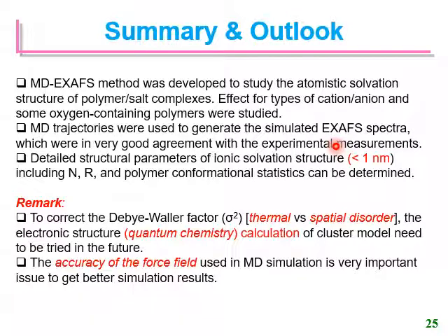So, summary and outlook. The MD-EXAFS method was developed to study the atomistic solvation structure of polymer salt complexes, and we studied the effect of the type of cation, anion and some oxygen-containing polymers. The MD trajectories were used to generate the simulated EXAFS spectra, which were in very good agreement with experimental measurement. And the detailed structural parameters of the ionic solvation structure can be obtained.